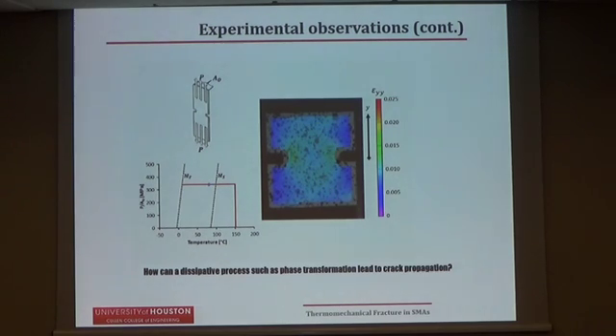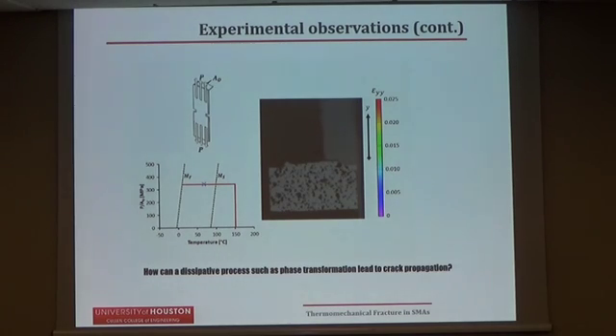I believe this is an intriguing response, very characteristic of shape memory alloys, because the general consensus is that phase transformation results in transformation toughening. Here what we see is that phase transformation during cooling initiates a crack, and the crack runs unstably. The reason that the crack runs unstably here is because this geometry is rather unstable due to the shape of the notches. This geometry stores a lot of elastic energy, and at the initiation of the crack, this elastic energy drives the crack growth to be unstable. So why does this happen?